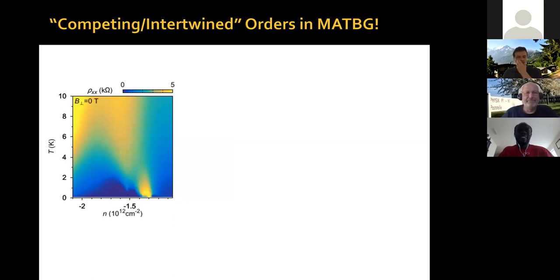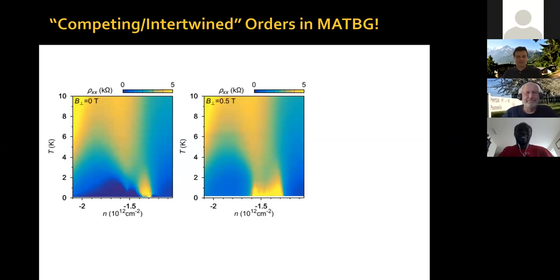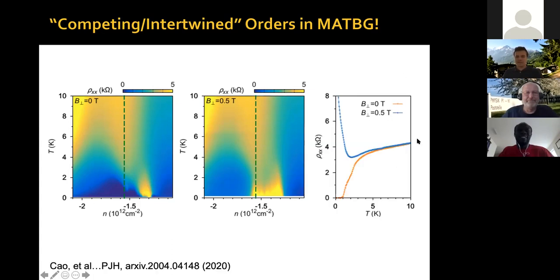We take this exact same device, we just apply a small perpendicular magnetic field, and what we see is the following. This region that had this depletion leads to an insulating state at low temperature once you suppress superconductivity. Let me show you these traces just to make it more apparent. At 0 magnetic field, the resistivity goes down and the system becomes superconducting. At a small finite magnetic field, the resistance goes up and becomes an insulator at the exact same doping, the exact same density. So we saw it once and weren't sure if this was a generic feature or not, but then you see it again and again, particularly in samples within a specific angular range.